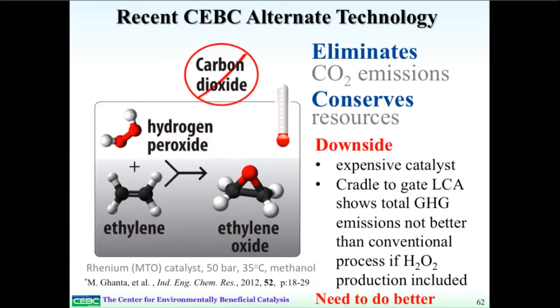Here, a rhenium catalyst is being used in a homogeneous catalysis formulation. The major downside is this is a pretty expensive catalyst. Rhenium is not cheap. And so we can do an analysis. The other downside is if we do an analysis of this using life cycle analysis, which is trying to understand both the economic impact and the environmental impact, we see that the total greenhouse gas emissions is not considerably better than the conventional process if you take into account what you need to do to form the hydrogen peroxide. So if you look at it from cradle to gate, basically looking at what you need to actually form the raw materials. Now we have a number of ways of trying to improve this so we can actually get that to be a lot better, but still, because of the expense of the catalyst, it's really not economically viable. So we really need to do better.